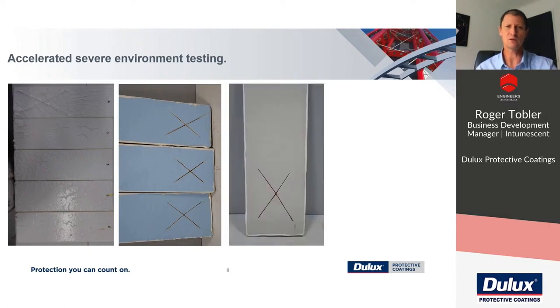So really good results. We then tested the intumescent on its own to understand how durable the intumescent is without a top coat, without a primer. And we got similar results to the panels on the left with the epoxy primer and the epoxy top coat. So it just confirms that epoxy intumescents are really durable to moisture exposure.